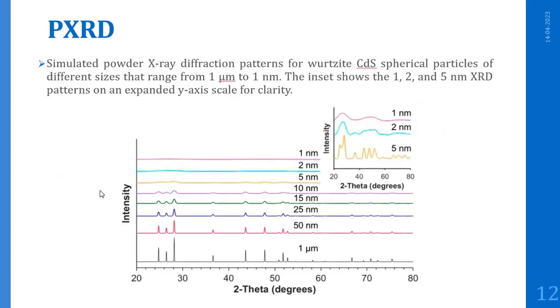Later on, there is a simulated powder X-ray diffraction pattern for wurtzite cadmium sulfide spherical particles of different sizes, ranging from 1 micrometer to 1 nanometer. In this figure, from bulk 1 micrometer to 50 nanometer, slight peak broadening is observed. It is difficult to calculate crystalline domain sizes using the Scherrer equation for particles in this size range, as most of the peak broadening is due to instrumental effects rather than particle size effects. Careful analysis is needed here.